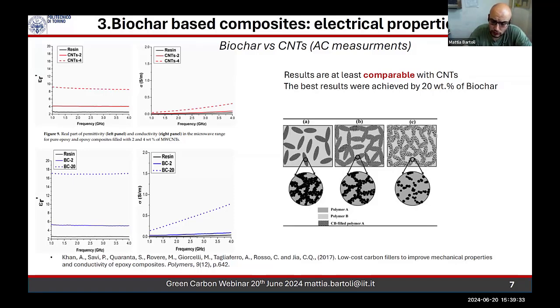From a more scientific point of view, we saw that biochar creates aggregates inside the polymers, creating bridges that can promote the conductivity. It is acting more like graphite chips, generally called potatoes because they are potato-shaped. But the point is, it is acting in this case as micrometric carbon. It is quite interesting because a micrometric carbon, with a particle size around 1-2 microns, can easily match a nanocarbon like CNTs from the conduction point of view.